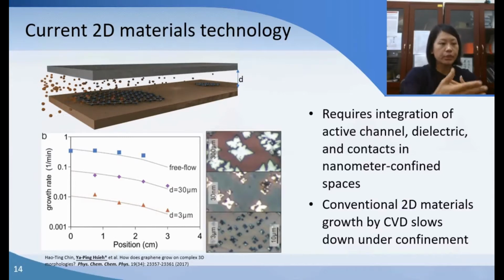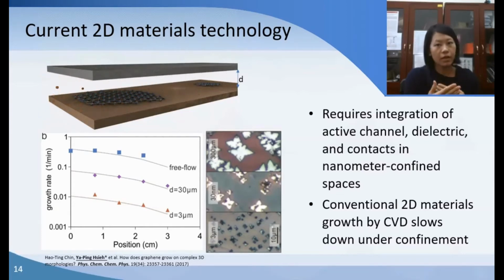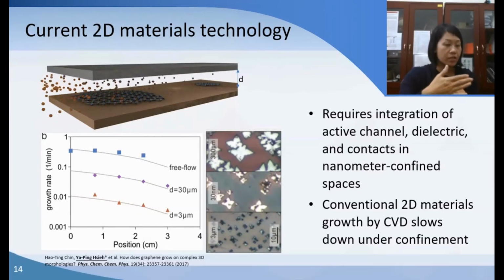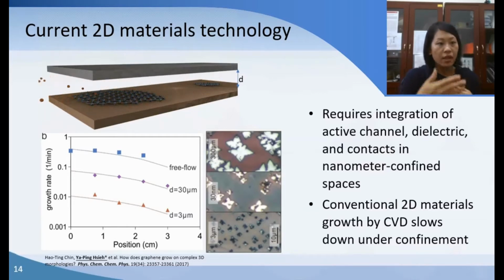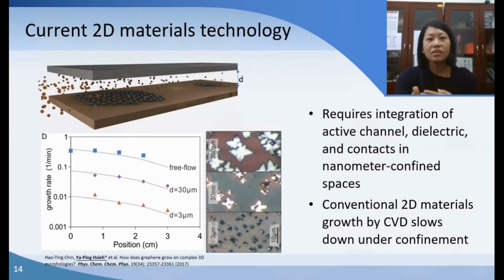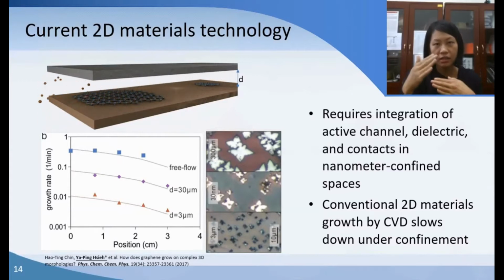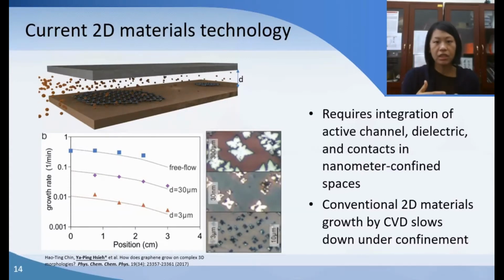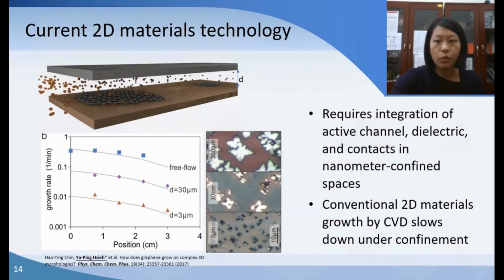So we first started with just putting a cap on the growth substrate and changing the gap and see what happens. And we found that as the gap getting smaller and smaller, the growth rate decreased a lot. Okay, sorry. The gap, as the gap size decreases, the growth rate also decreased by a lot. And so by this rate, when we reach nanometer gap size, we expect almost nothing can be grown. So we were very worried about that.